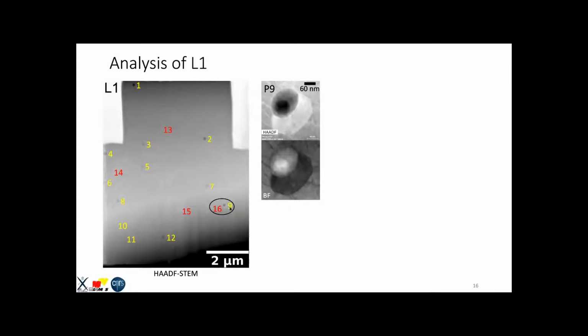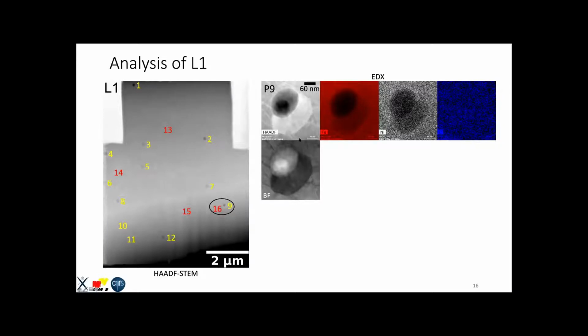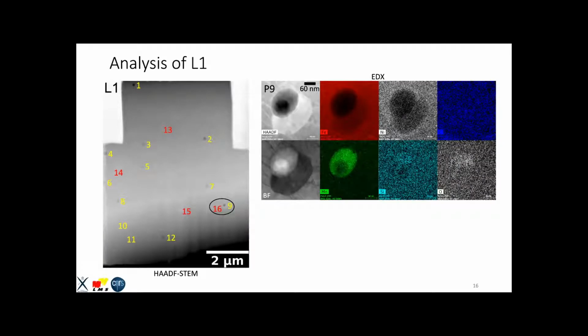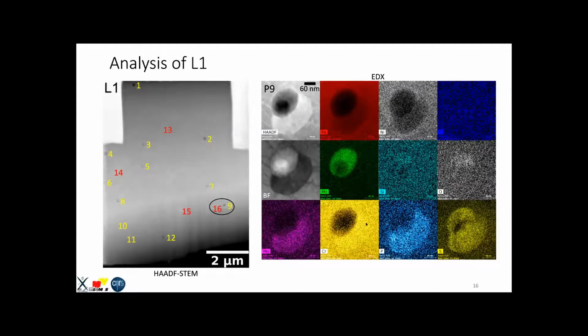So this was the first precipitate that we characterized, and we found something very weird, that it had contrast everywhere that was different from the surrounding matrix. When we did the EDX characterization, we saw that, okay, there was only one part of it that was manganese silicon oxide. The rest turned out to be rich in molybdenum, chromium, phosphorus, and sulfur. Okay. Now, this is something that was unexpected for this material. As I mentioned before, the literature was consistent on saying that precipitates in additively manufactured material, 316L stainless steel, are